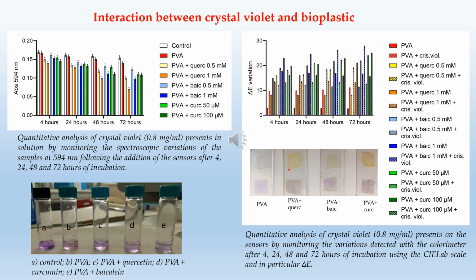Again, the ability to detect the presence of organic pollutants, crystal violet and phenol red, in solution was also analyzed. As it is possible to see from the graph, PVA and polyphenol-based sensors at different concentrations are able to decrease the amount of crystal violet present in solution, also resulting in a colorimetric variation of the sensor itself from yellow to violet. In particular, solutions containing crystal violet at a concentration of 0.8 milligrams per milliliter were placed in contact with PVA plus polyphenol sensor squares.